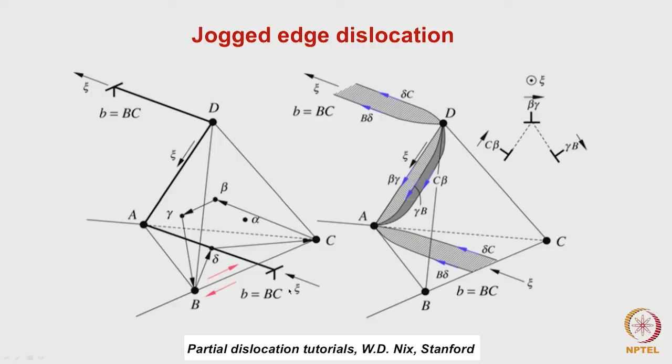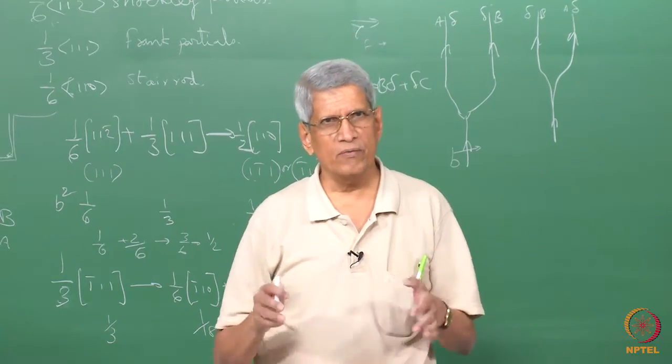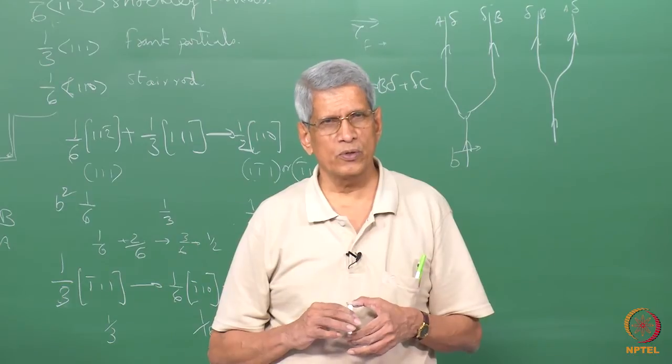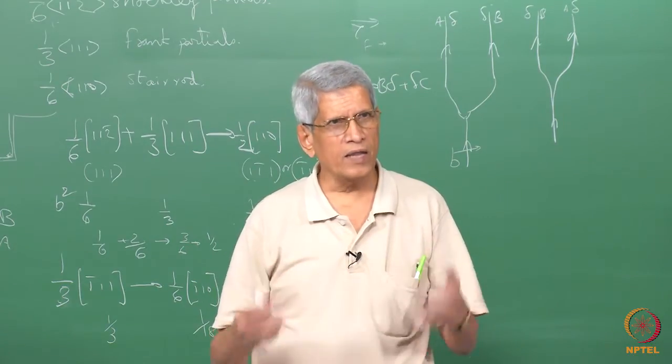This is how the perfect dislocation looks, because in this Thompson tetrahedron it is easy to visualize. Now this is split into partials, forming a constriction. Then here, when this has separated, it has just formed a stair rod dislocation, and the other part of the stair rod dislocations are there. Then this part of it, in the parallel slip plane, has also split into partials. Now when you look at it, you can visualize in 3 dimensions how these dislocations are lying. That visual feeling we get when we use the Thompson tetrahedron to write or draw all the dislocation reactions.